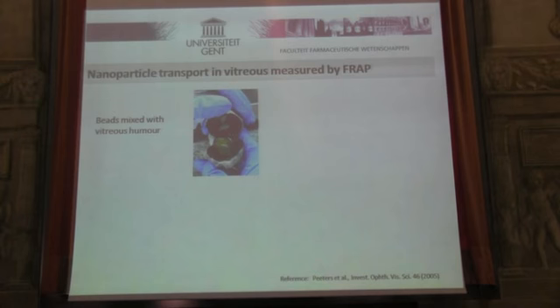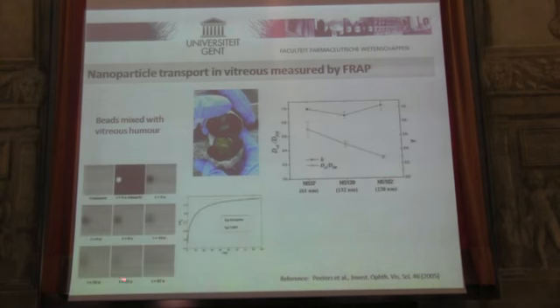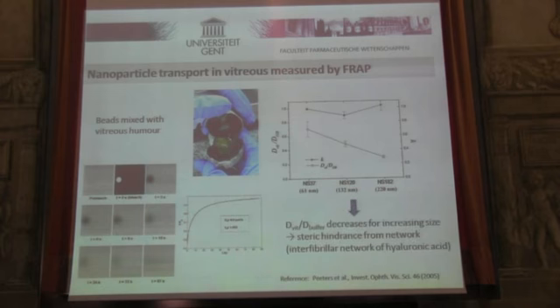So the first experiments that we did is we actually took out the vitreous gel and then we physically mixed it with these particles. We do FRAP experiments indeed on the vitreous gel here. You can do these mobility measurements, and then we noticed that relative to water, larger particles have more hindrance to move through it as compared to smaller ones. And this could be caused by steric hindrance. So not just viscosity, but by steric hindrance because of the polymer network inside the vitreous.